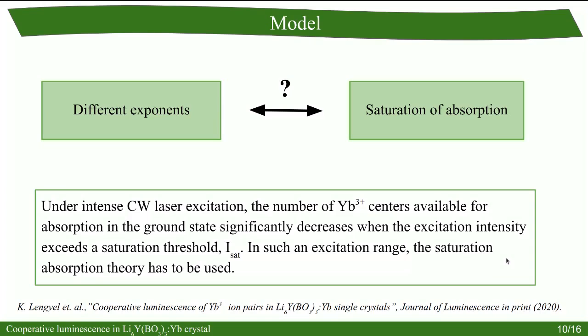The saturation of absorption means that under intense continuous wave laser excitation, the number of the ytterbium centers available for absorption in the ground state significantly decreases when the excitation intensity exceeds a saturation threshold, the so-called saturation intensity. And if we are in this regime, then the saturation absorption theory has to be used. This can be read in detail in this article, which is now in print.